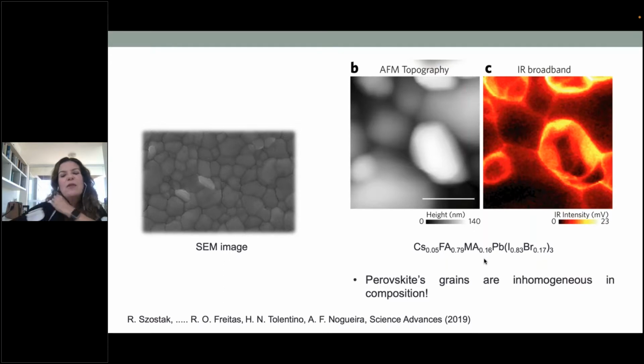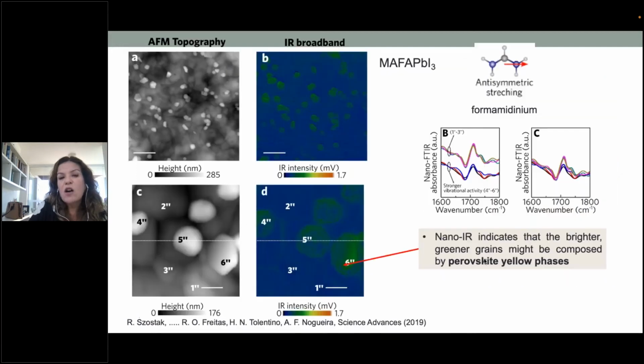What I believe is that close to the grain boundaries, we have a depletion of these organic cations. But also, as I mentioned, you can collect point spectra. For instance, this is again the AFM on the left, the infrared broadband on the right. This is with a higher magnification. For instance, you can choose the grain that you want, and you can get a single infrared spectrum of the